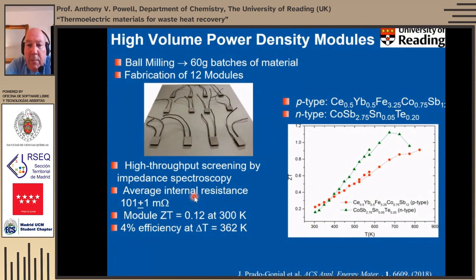Now, despite the fact we get materials with high ZTs, so here are the materials that went into these high volume power density modules, we're at ZTs of about 1.1 to 1.2 maximum. The module ZT at 300 Kelvin, so down here, is only about 0.12, whereas the materials themselves are maybe about 0.2, just above. So we lose a lot of performance in fabricating the module due to contact issues and so on. But nonetheless, we do get something that's about 4% efficient at a delta T of 362 Kelvin.